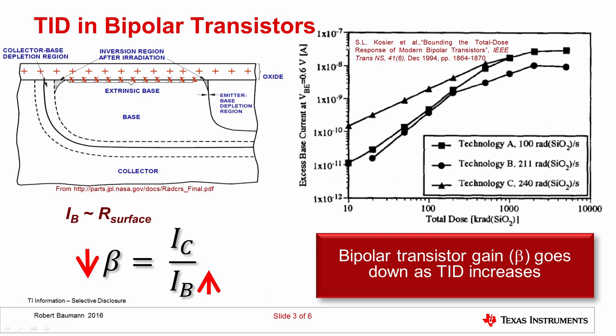The external circuit has to force a lot more base current to get the same collector current. Effectively, your HFE or beta of your bipolar transistor is going down. We can see on the right-hand side that as total ionizing dose increases, the base current goes up — on a log scale, going from 10k rad to 100k rad, we see roughly a 50x increase in base current. So bipolar transistor gain degrades significantly as total ionizing dose increases.